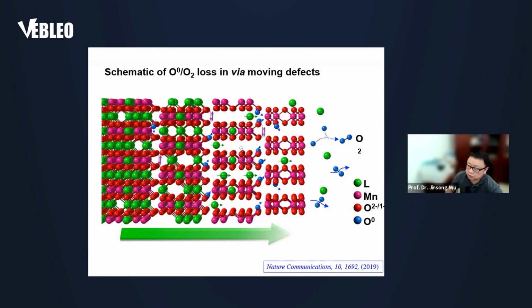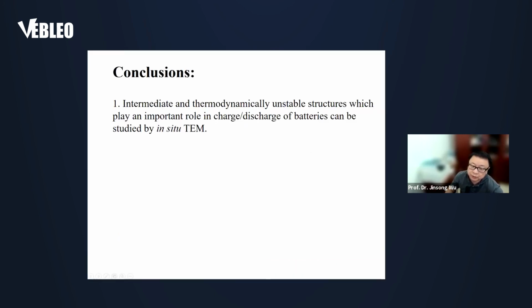And once the electrode loses a lot of oxygen, the capacity will decrease. At the same time, the voltage will be greatly decayed, which becomes a big problem. So this is the mechanism we found by using the in-situ TEM.